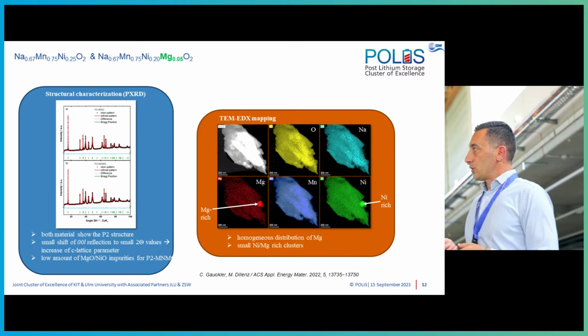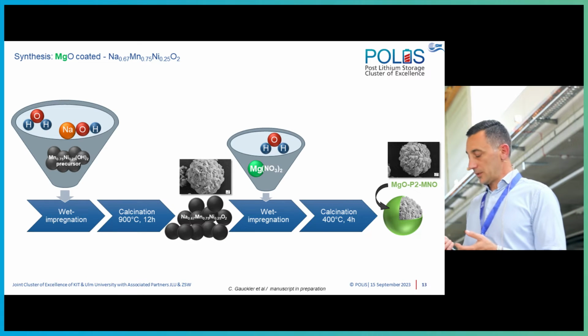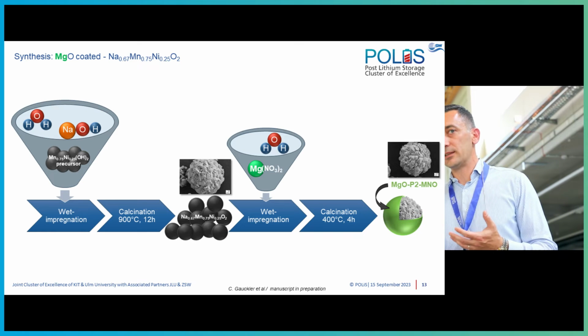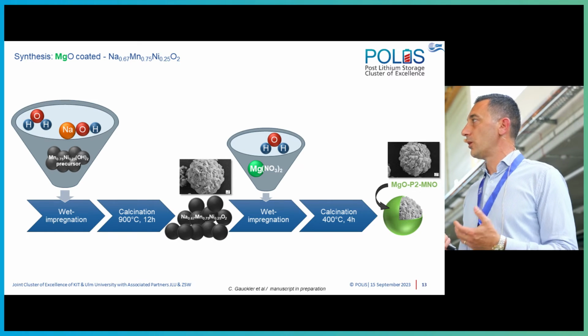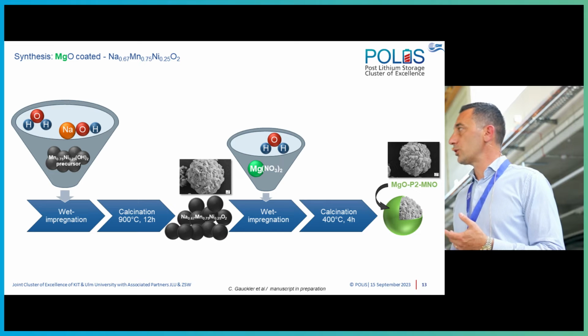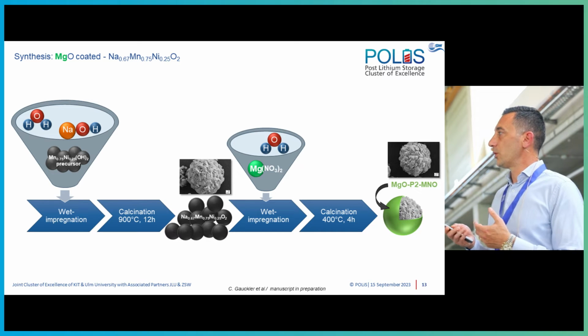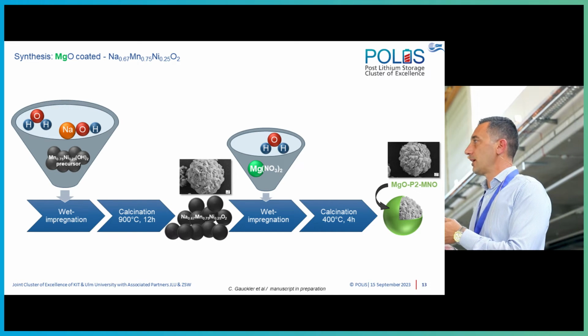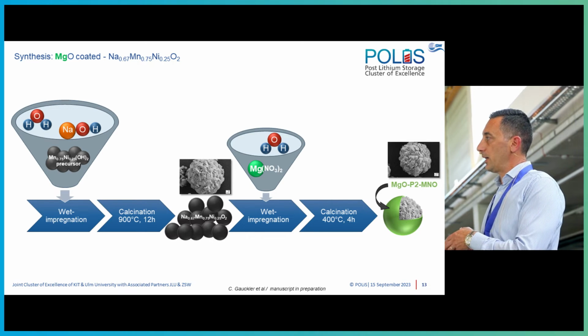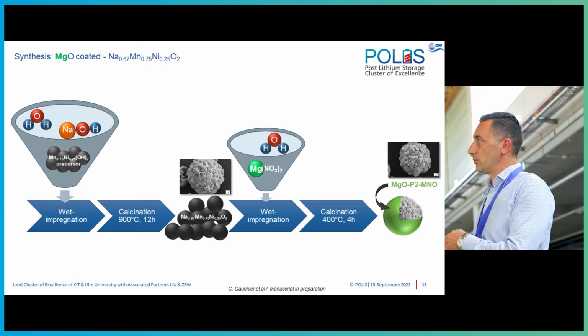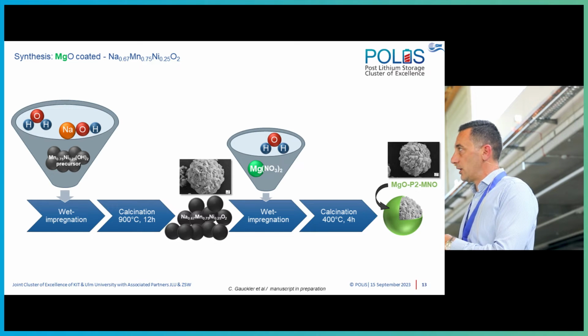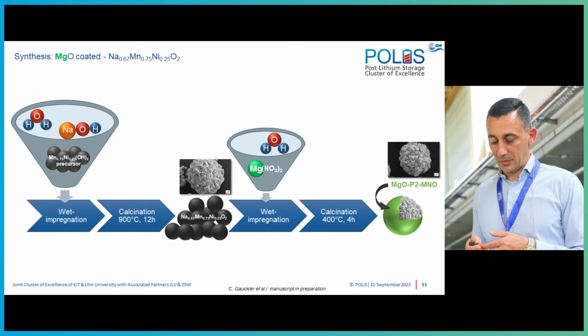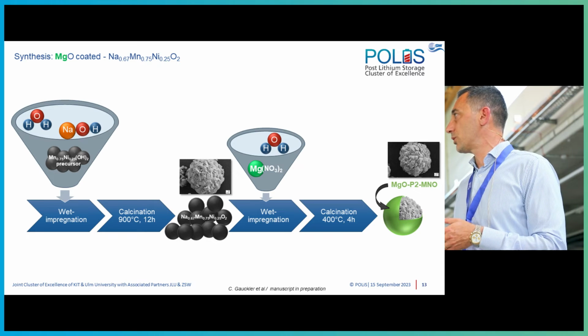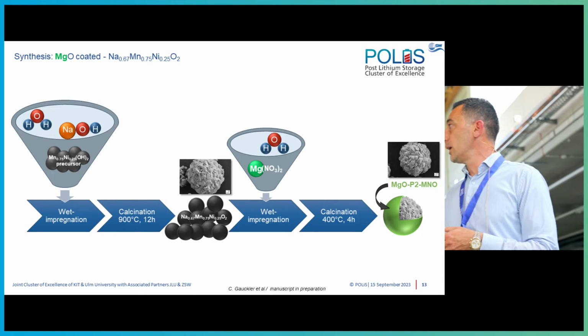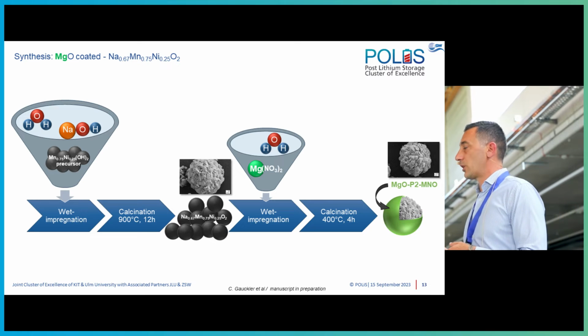Now, what happened actually, if we want to make the coating and we want to prevent the doping, we have to follow a different approach. So, of course, what we did was, after getting the baseline material, we did wet impregnation using a magnesium nitrate source as a source of magnesium, of course, and then we did the calcination at 400 degrees C.